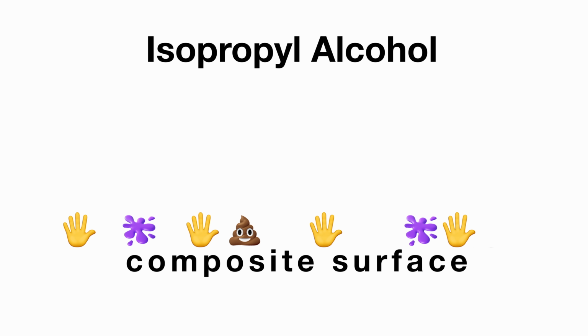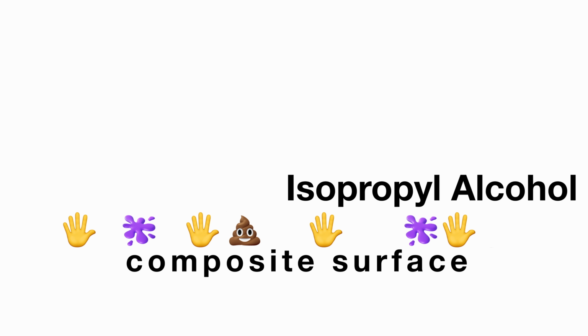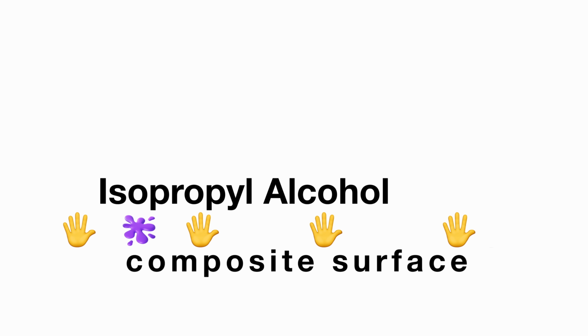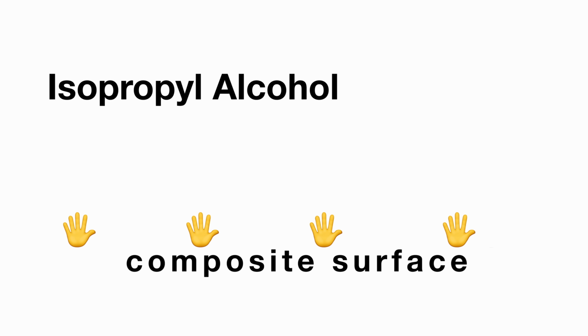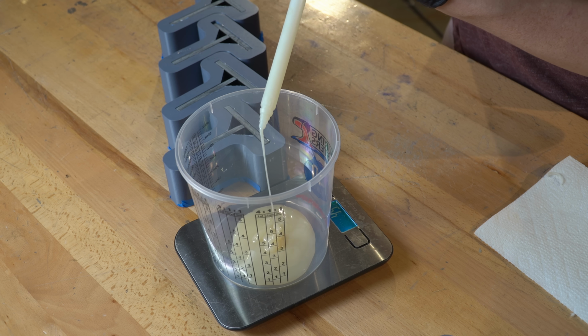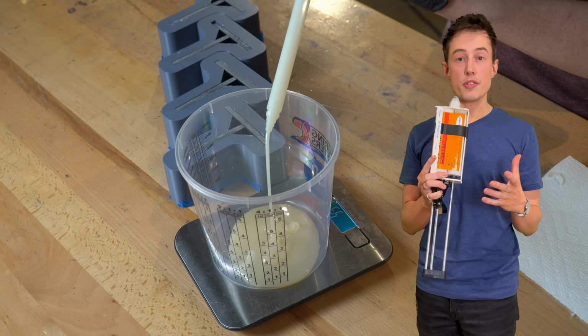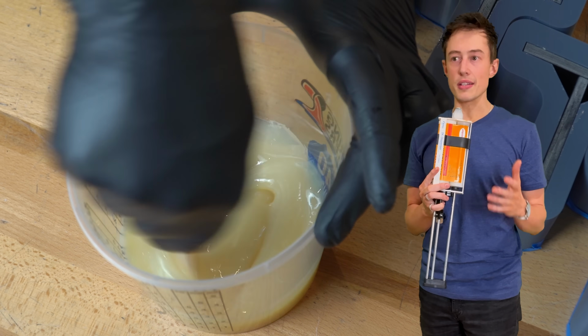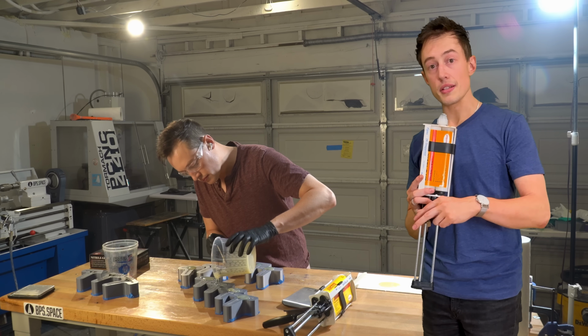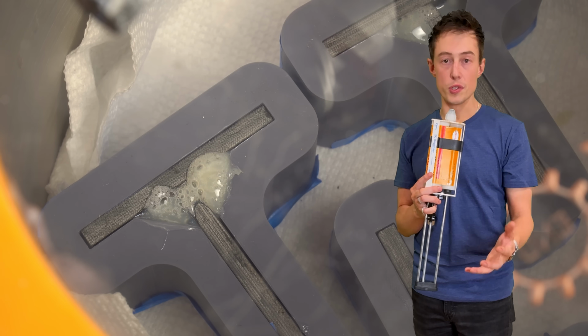Coming in with IPA after the acetone will further help clean up residue from dissolved oils and contaminants. Sometimes these aren't fully removed by the acetone because of how fast it evaporates, and wiping them off with a lint-free wipe and IPA will further clean the area. For these first 4, I hand-mixed a batch of epoxy, degassed it in the cup, poured it into the molds, and then re-degassed the molds before letting it cure.